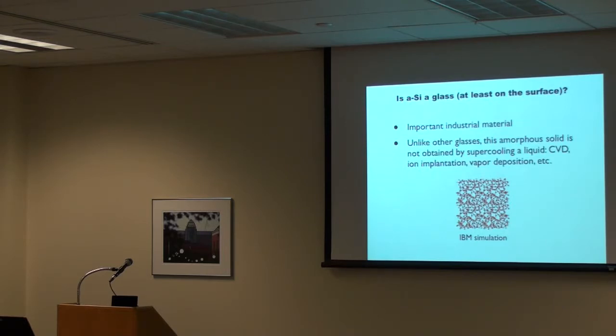But you can't actually make amorphous silicon that way. So I cannot take liquid silicon and cool it down, because all you're going to get is crystalline silicon, because you just can't do it fast enough to get the amorphous one. So usually the way it's done, it's grown by vapor deposition or by ion implantation, which are actually the two examples I'm going to show you here of how we did it. So you could actually take crystalline surfaces and damage the heck out of them until they're amorphous, or you could have a very cold surface and deposit silicon atoms on it one by one from the vapor, so they kind of just freeze in place and make the amorphous solid that way.